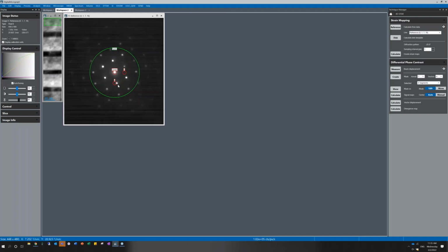In this diffraction image, you specify the central beam. You want to change the size of the selections by changing the size of these red circles to contain the diffraction spot and also some tails from this center beam, because this is what the software is going to use to calculate a template to find the rest of your reflections.